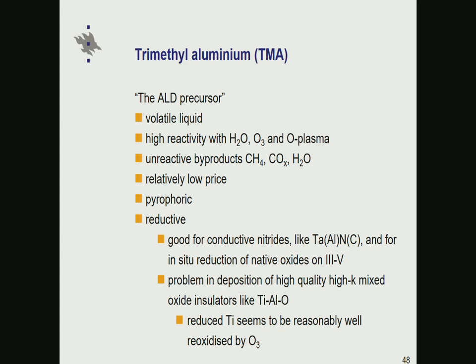It's also exploited in what is called the self-cleaning effect nowadays when depositing oxides on III-V compounds, which typically have a native oxide, like gallium arsenide, which is partially oxidized from its surface. One pulse of TMA removes the oxides because aluminum is eating the oxide away there. So this is kind of a good thing.